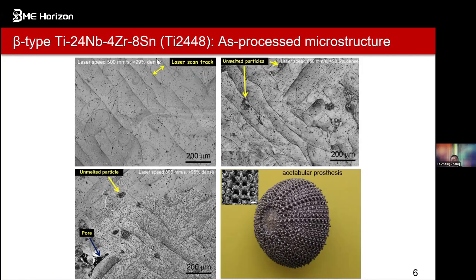Of course, this is presented by dark bands, which are clearly visible under the microscope. And these tracks are typical microstructure features in samples manufactured by 3D printing. For the nearly fully dense parts, the powders have completely melted or fused, and there's no apparent porosity in the microstructure. But for the samples with intermediate density, unmelted particles are evident in the microstructure. You can see there are still incompletely melted particles.